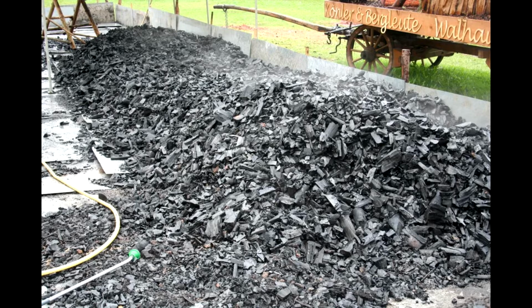As a result, smelting operations, which require truly prodigious amounts of charcoal, had to take place near supplies of wood. Sim and Ridge, original citation, note that transport beyond 5 to 6 kilometers would degrade the charcoal so badly as to make it worthless. Distances below 4 kilometers seem to have been more typical. Moving the pre-burned wood was also undesirable because so much material was lost in the charcoaling process, making moving green wood grossly inefficient. Consequently, for instance, we know that when Roman iron-working operations on Elba exhausted the wood supplies there, the iron ore was moved by ship to Populonia on the coast of Italy to be smelted closer to the wood supply.